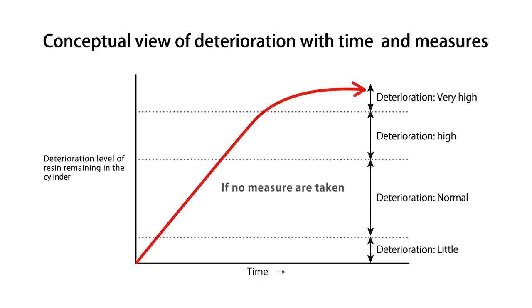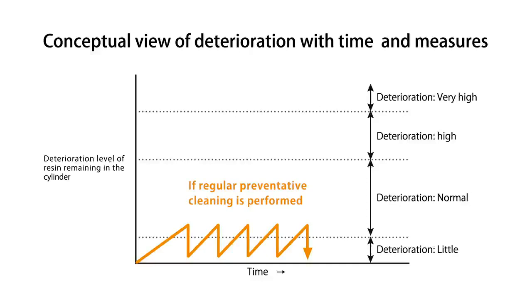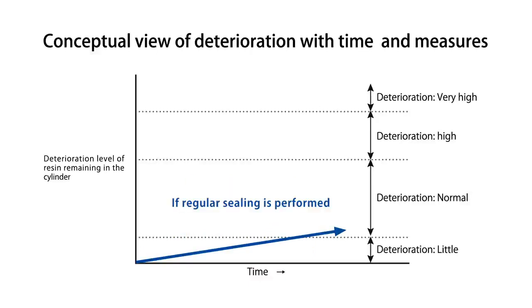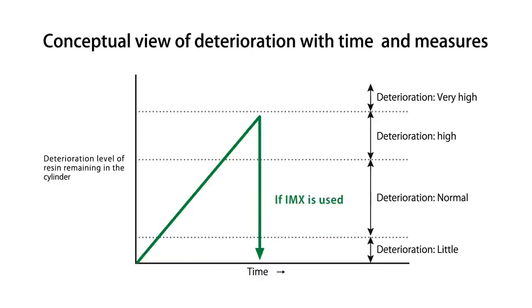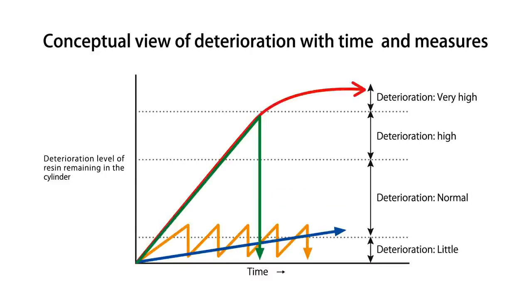In summation, if no measures are taken, the resin remaining in the molding machine deteriorates increasingly with time, as shown by the red line, until it finally reaches a level that requires a thorough manual screw cleaning. In contrast, the orange line shows the improvement of the deterioration level if regular preventative cleaning is performed. Next, the blue line shows the improvement in deterioration by regularly sealing. Lastly, the green line shows the removal of deposits and contaminants using IMX. IMX exhibits its effectiveness when the stains cannot be removed by regular cleaning agents. Failures caused by deposits and contaminants can be prevented by conducting these procedures on a regular basis. Please be sure to implement these procedures.